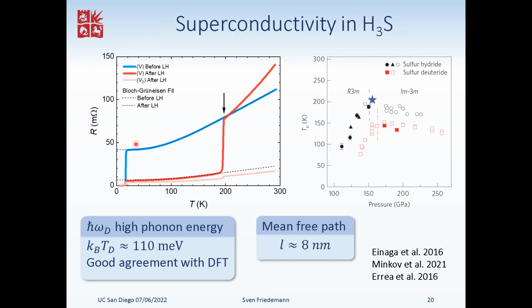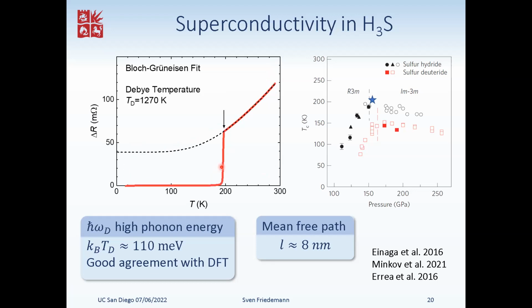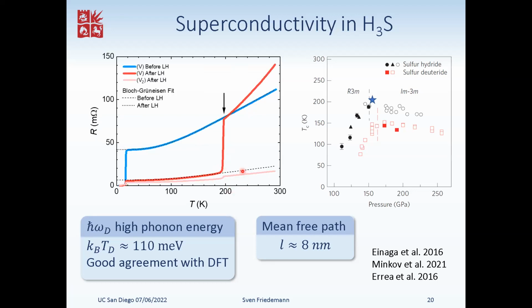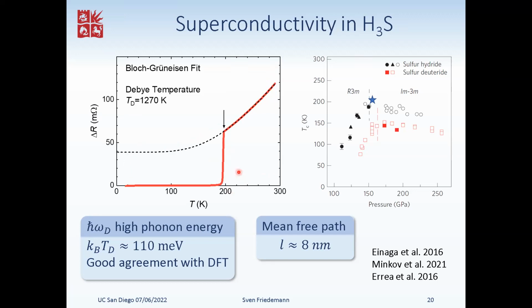If we fix those coefficients that we obtain from the elemental sulfur and attempt the fit to this residual resistance, we see that this is indeed consistent with elemental sulfur and an increased purity of the sample, and then we can subtract this. So that's essentially taking the red curve and subtracting this dashed line down here. Then we get the resistance contribution from this H3S bit of the sample. This assumes that we've got indeed a serial resistor network from the sample stretching on.